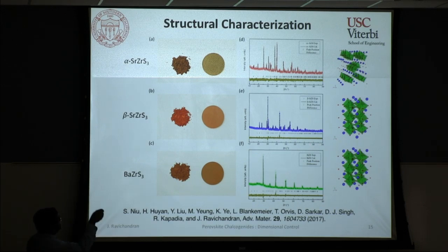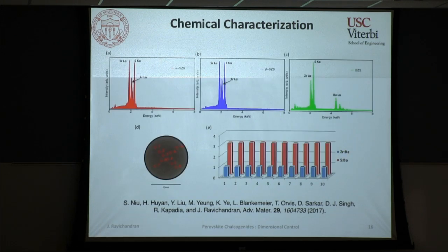So our first generation materials were all powders, but nevertheless, structurally they were looking really good. We also did some chemical characterization of these materials using EDS and X-ray fluorescence studies, and we found that consistently, in a semi-quantitative manner, they had the stoichiometric ABX3 composition, even globally and also locally.